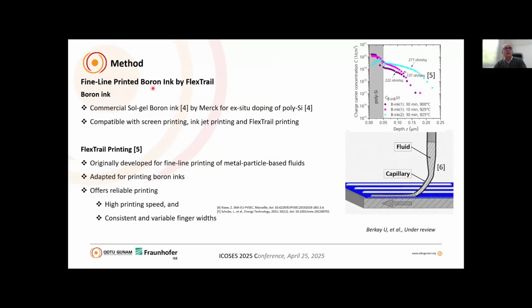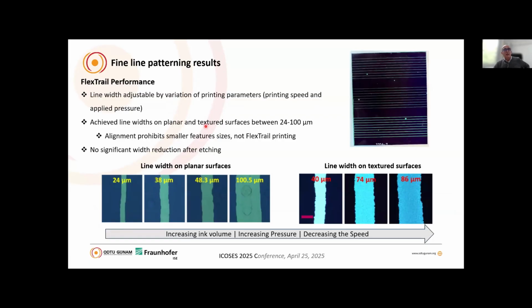This fine line printing has been done together with Fraunhofer ISE, and this paper is published, by the way, in Progress in Photovoltaics. Here, the boron ink is printed by using a technique called FlexTrail. More details can be found in these papers. We have been able to make fine line printing by using this FlexTrail technique. It provides a high printing speed and also a very consistent and variable finger width, so we can control the finger width very nicely. You see some pictures here, and we can have printing down to 24 micrometers. This can be even reduced, but we haven't tried that yet. Different finger widths can be obtained in this way on planar and textured wafers.